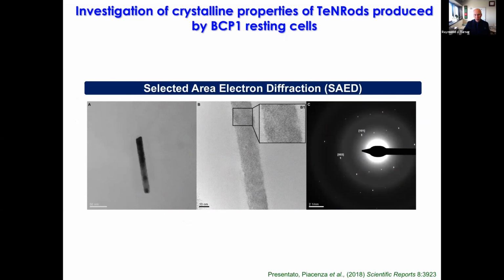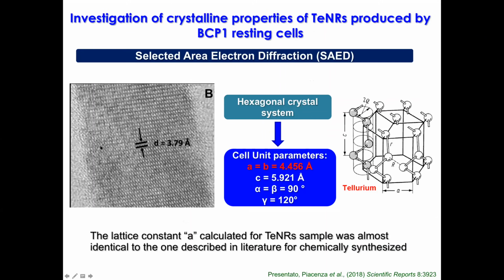The quality of the material, here we're doing selected area electron diffraction. We extracted and purified some of the nanorods. You can see a really nice diffraction pattern here. Zoom in, and the unit cell lattice is extremely close to what is in the chemistry one.